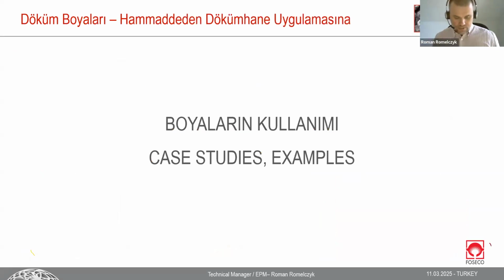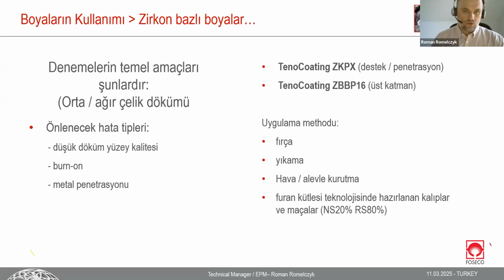Yeah. Some examples of usage from real life. So we can say case studies. So here we talk about pure zircon-based coatings. ZKPX, maybe you remember, is a penetration coating, an impregnation coating, which we can say improves quite deeply, because it's more than 7-8 millimeters deep, the refractory of the mold or core. It also prevents the possibility of metal penetration. And ZBBP16 is a coating which builds the external layer. This layer will face